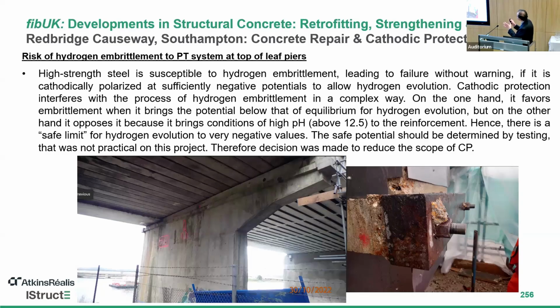So CP, in a sense, interacts with high tensile steel in a complex way, because on one hand, there is a risk of hydrogen evolution, but on the other hand, it increases the alkalinity around the reinforcement as well, which helps control this phenomenon. As a result, there is a safe limit, which has to be determined by testing the steel. For example, in this case it was Macalloy bars, but because of the condition of the system, the condition of the bars, and the practicality, we couldn't take a sample and test it. Hence, at the end, a decision was made to reduce the scope of the CP system to avoid failure of the PT system.